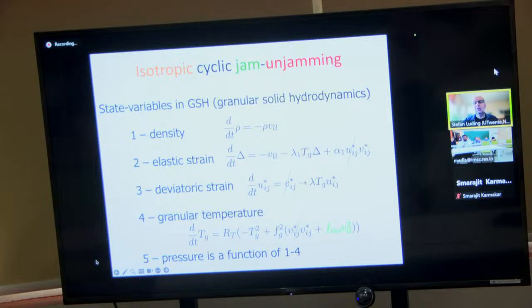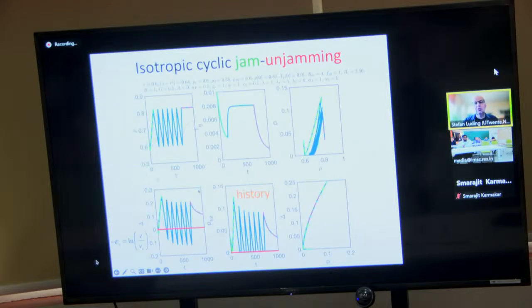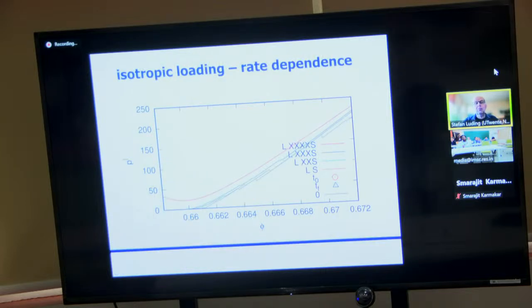If we go to the isotropic special case, a few terms in the theory drop out, and we can analyze the complete theory, all the state variables under some situations. I want to skip the details here, but I want to show you the strain rate before my time is up. This is pressure as a function of density, so related to some of the plots which I showed you before, and the different colors mean different rate. Okay, so the red line, which is actually hidden by the others below here, below the gray line, is the slowest. The magenta line, this one, is the fastest compression, and every x stands for one order of magnitude in compression rate. So the data set contains 5 orders of magnitude in compression rate.